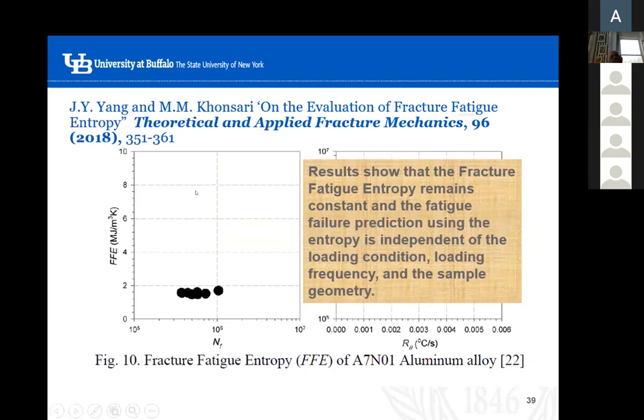Here is an example. But entropy is not measurable. For example, from an engineering point of view, the stress is measurable. We can measure load by area in a generic sense, particularly in high cycle fatigue. There is not much change in cross section. High cycle fatigue failure is without much geometrical change. So force by area, whereas the entropy calculation for high cycle fatigue, I don't know, because I have no insight about this, but people should see it from a real application point of view. Scientifically, what you say is very good, from a mechanics point of view. But from an engineering point of view, for me, it is very easy to get the life from the SN curve. I think people have been living with that for several decades.